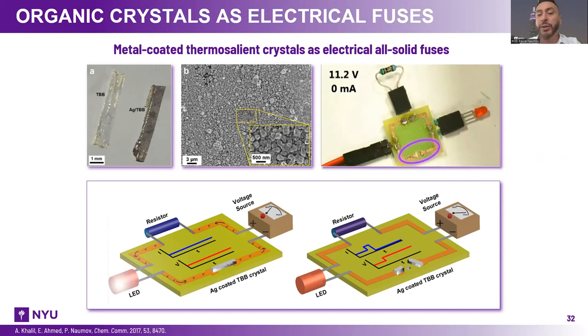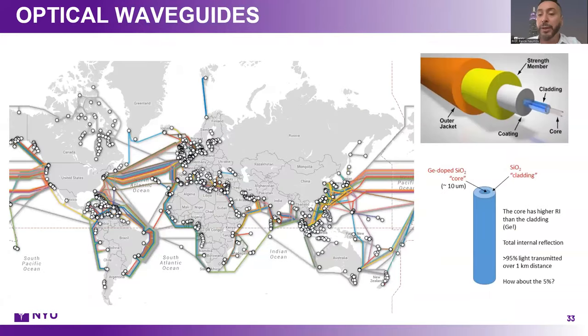And so this is a so-called solid-to-solid fuse, which overcomes the so-called arcing problem that is encountered with metals or metal alloys, where we have partial evaporation. So keep in mind, in common fuses, we have melting. And melting can lead to partial evaporation, and that can establish a short circuit. In our case, we only have a solid-to-solid transition, so there is no evaporation, and this overcomes the arcing problem.